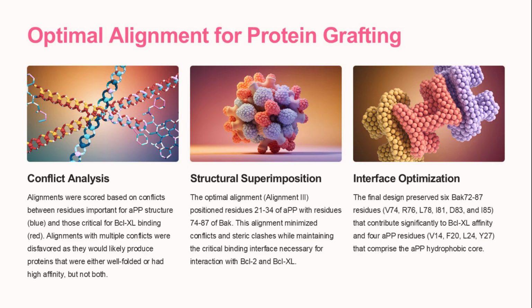Alignments with multiple conflicts were disfavored, as they would likely produce proteins that were either well folded or had high affinity, but not both. The optimal alignment, alignment 3, positioned residues 21-34 of aPP with residues 74-87 of BAK, minimizing conflicts and steric clashes while maintaining the critical binding interface. The final design preserved 6 BAK 72-87 residues that contribute significantly to BCL-XL affinity, and 4 aPP residues that comprise the aPP hydrophobic core.